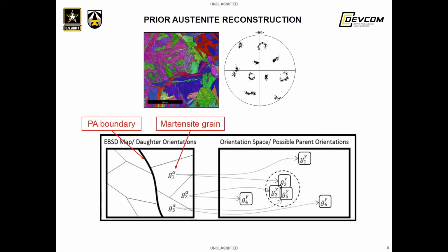So the reconstruction algorithm, which I'll describe briefly, has at its core a neighbor-to-neighbor comparison of martensite grains or laths. The schematic at the bottom depicts this in a concentrated form. The left side of the schematic depicts a 2D spatial region of the scan, where you have two groups of martensite grains that are divided by a prior austenite boundary that we have yet to discover.